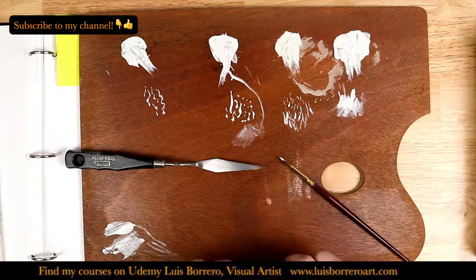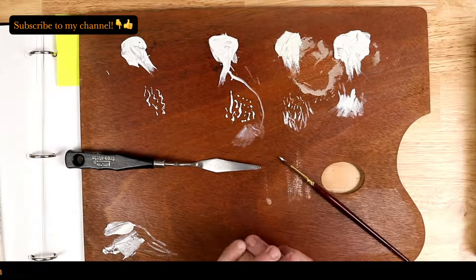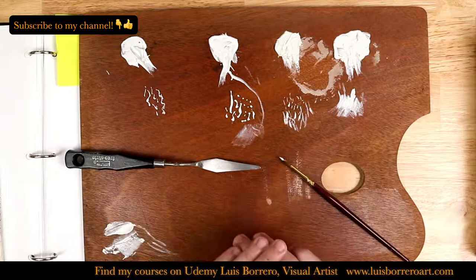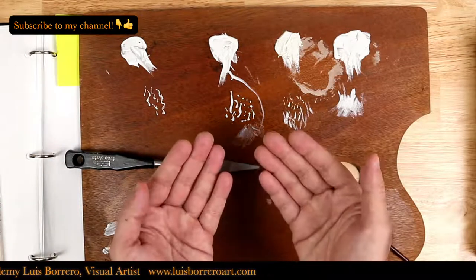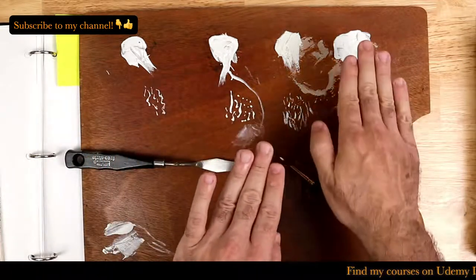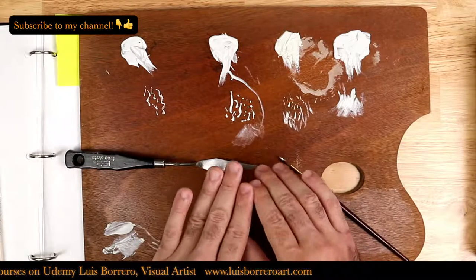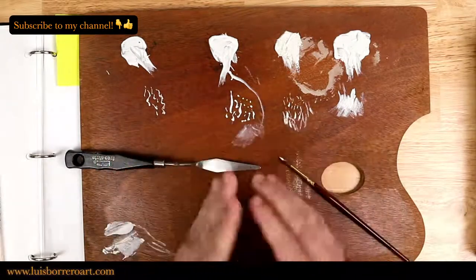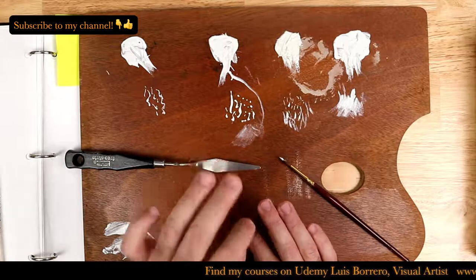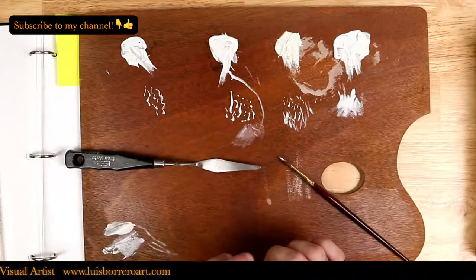Ron is asking, what about poppy seed oil? Poppy seed oil was used by a lot of Dutch painters from the 17th century and Belgian painters. Now, the consensus on poppy seed oil by the National Gallery Technical Bulletin is that it does not yield a film that is very flexible, like linseed oil. Linseed oil really has superior qualities, and second to that is walnut oil. And if you heat body the walnut oil, it's further improved. So I don't really use poppy seed oil. It was not very popular. There are some still life painters that used it with a lot of success to get a very, very beautiful, very smooth type of paint.